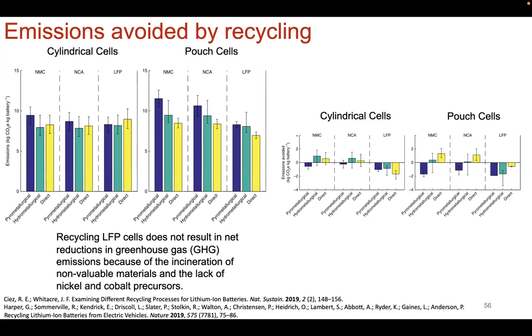So if you look at the emission, the amount of CO2 equivalent that's produced for NMC, NCA, and LFP in cylindrical versus pouch cell, for recycling, if you go through the pyrometallurgical or hydrometallurgy or just direct recycling, so that means you just take the battery out and you pop it in something else. If you look at LFP, you see here, okay, direct recycling, interestingly enough, there's an increase in emissions of CO2.